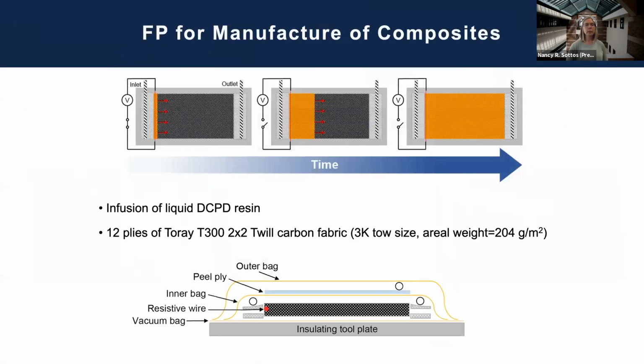And so, as I mentioned, this is going to happen from the liquid state. So we have a working time of several hours. And the way that we've chosen to make our composites in this initial work is using a resin infusion process. In particular, we're using a vacuum-assisted resin transfer molding process and infusing our DCPD monomer into woven fiber mats. In this case, it's a Toray twill carbon fabric. And basically, everything else, once you infuse the resin, it's very similar to a normal RTM process, except that we're just going to initiate this with a small heat trigger.